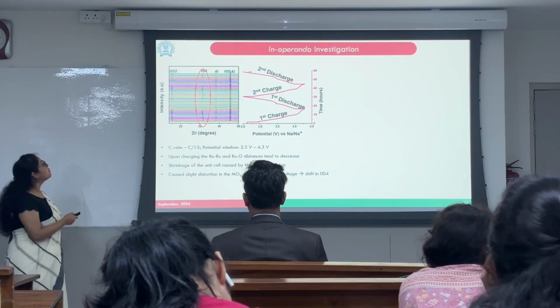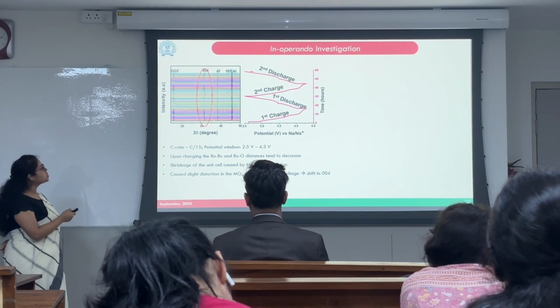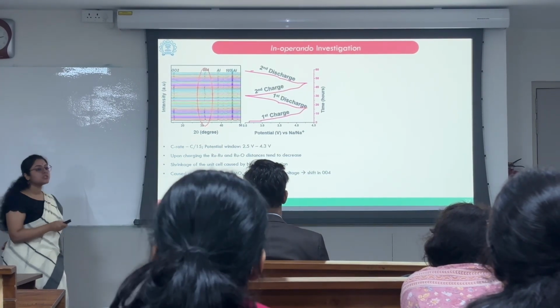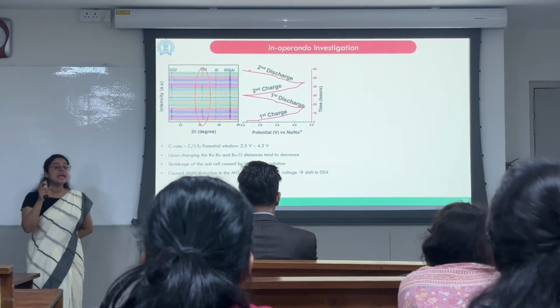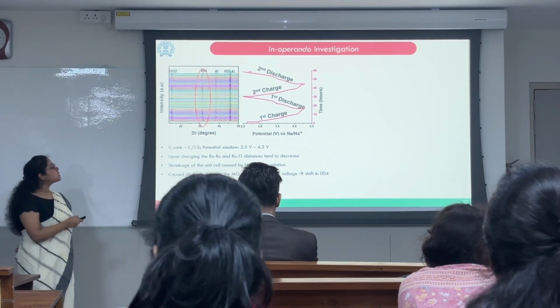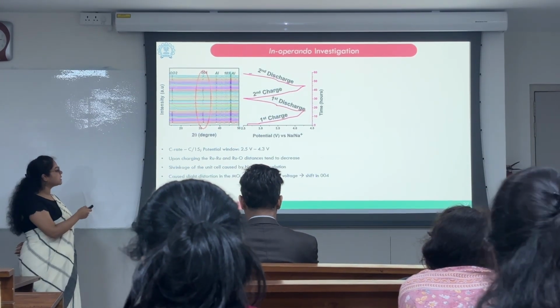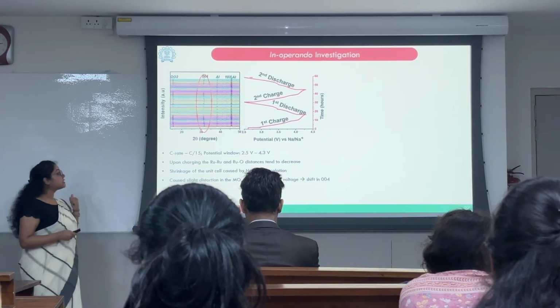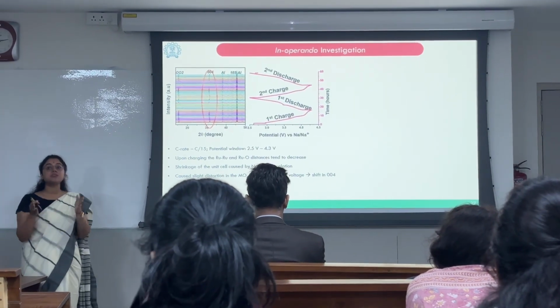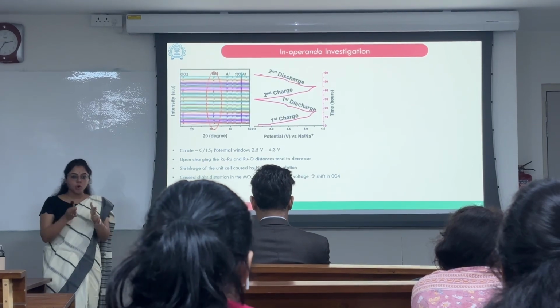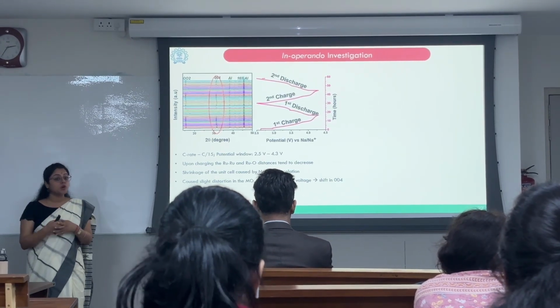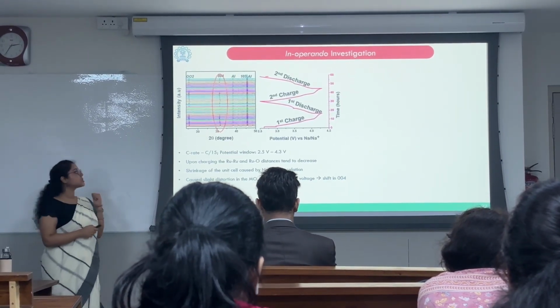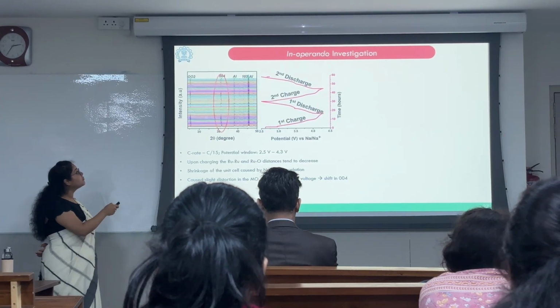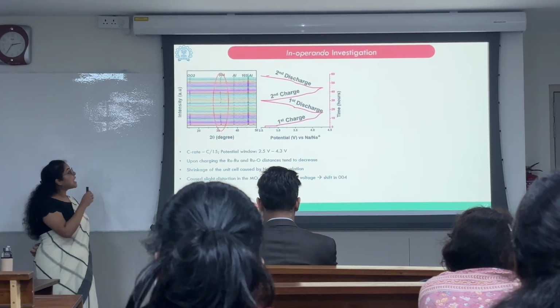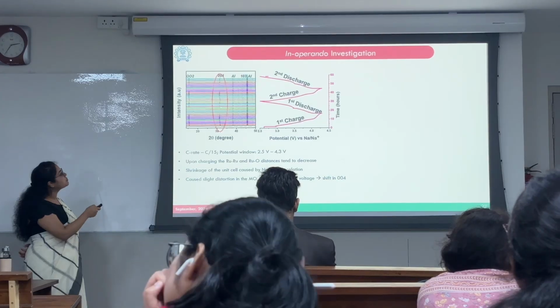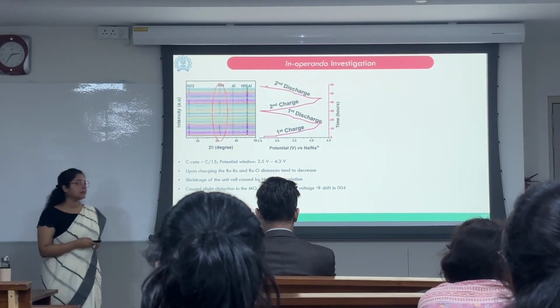So through the in situ X-ray diffraction analysis at a slow rate of C/15, we observed that during charging, the 004 plane, which is attributed to the changes in the MO6 octahedra, was seen to shift towards the lower 2 theta, which suggests that at this point there has been a reduction in the ruthenium-ruthenium bond and also the ruthenium-oxygen bond, which leads to the shrinkage of this MO6 octahedra, giving this variation during charging, which returns back to its original position after one full cycle.